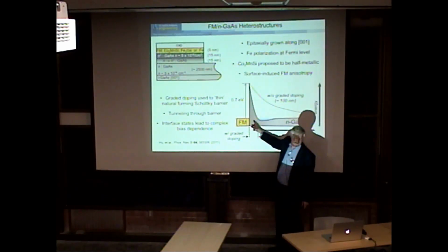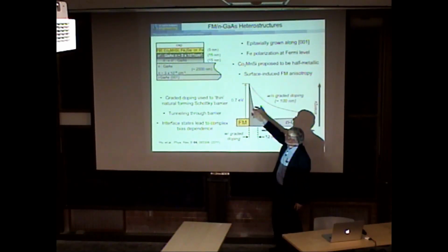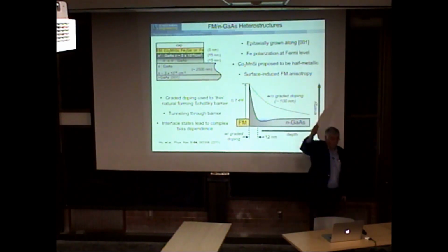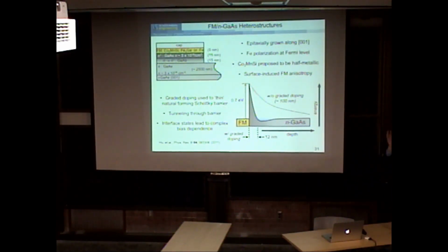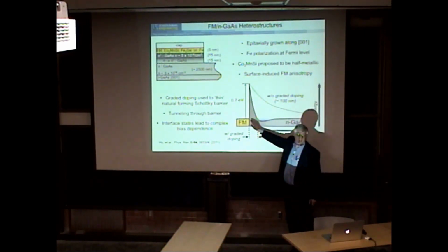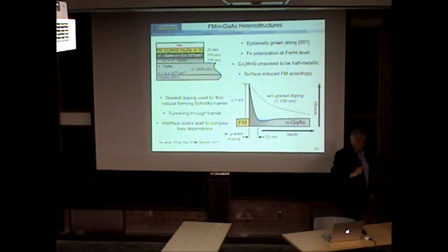Okay, by doping. The barrier with any ferromagnet? Well, just about anything you put on gallium arsenide is going to be between 0.6 and 0.9 eV, because the Fermi level pinning position from surface states is more or less mid-gap in gallium arsenide. So that's why it works.